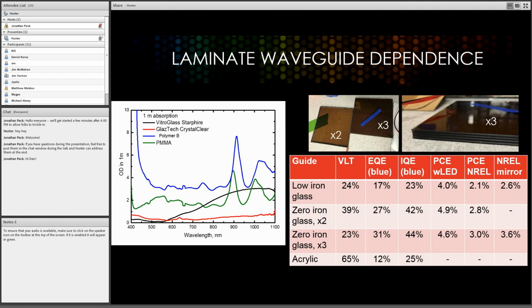I'm not even showing the data here, but we have a paper that you could look at. Here I'm comparing acrylic, which is a common waveguide that people use for luminescent solar concentrators, with low iron float glass and with zero iron float glass. On the left, you can see some absorption spectra, which is estimating the optical density through a full meter of the glass. And polymers are not that great, especially as you go into the near IR. They have some overtones that absorb, CH vibration overtones that absorb strongly there.